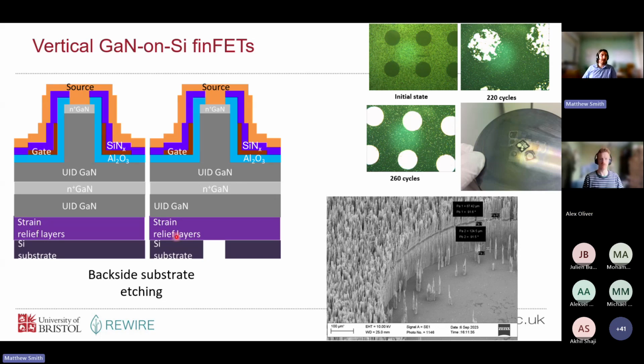Yeah, I think it should be. I mean, this silicon deep etch process is the Bosch process, which has been around for a while. It's what we use, so it's quite well established. So far we've worked with single fin devices. So if you want to scale the current up, one thing we can do is increase the length of these fins.